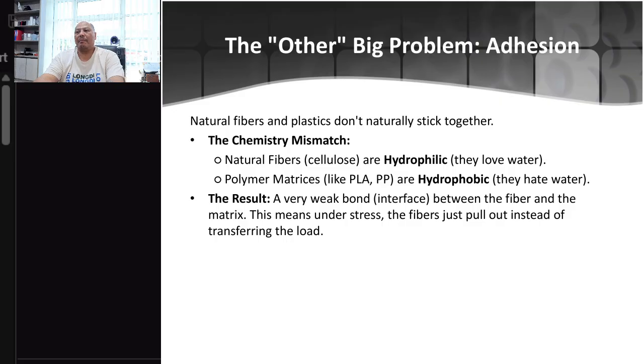Okay, then the other big problem is adhesion. Adhesion is the key. Natural fiber and plastic do not naturally stick together. This is the chemistry mismatch. Natural fiber cellulose is hydrophilic, they love water, while polymer matrices like PLA or PP are hydrophobic, they hate water. As a result, there is a very weak bond at the interface between the fiber and the matrix. This means under stress, the fiber just pulls out instead of transferring the load. You know what I mean?